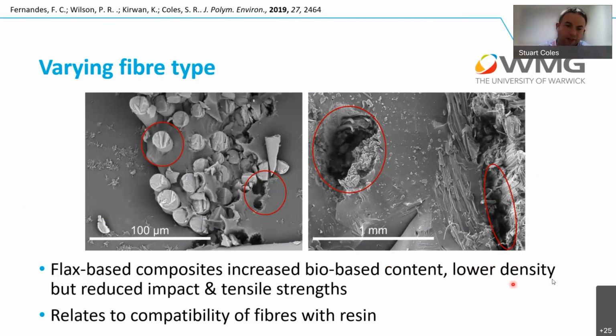with the change of the fiber type, we were getting some increased levels of bio-based content, which is obviously very good, and with the natural fiber, a lower density, which is great for lightweighting if we're thinking of putting it into automotive applications, but the mechanical properties were lower. And we were getting reduced impact, reduced tensile strengths, and we found that the compatibility of these fibers with the resin wasn't particularly great. So our optimized epoxy resin didn't really seem to be entirely compatible with the fibers. We were getting lots of fiber pull out, as you can see here, lots of void content. It didn't look to be a particularly brilliant polymer composite.